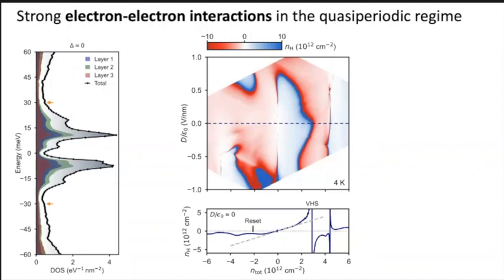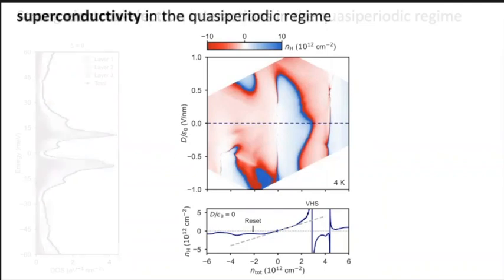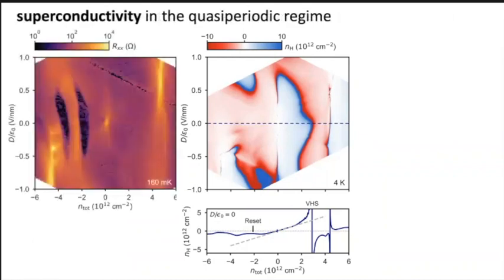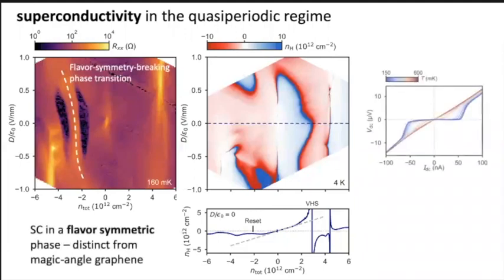And you can have things like Fraunhofer singularities, and you can have things like resets where you deviate from this linearity, okay? These are due to strong interactions and typically symmetry breaking phase transitions in your spin and valley degrees of freedom. If you look at this at zero magnetic field and at lower temperature, in your resistivity you find this region. This is where the flavor symmetry phase transition takes place. And you can see that on both sides of this, you actually have superconductivity, okay?